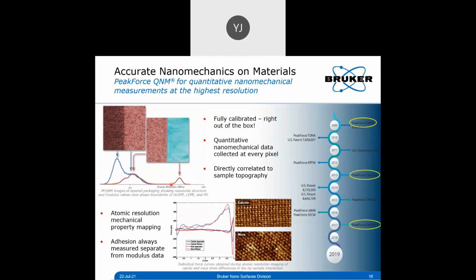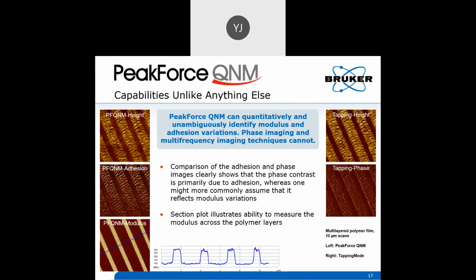Yeah. So now I want to talk about nanomechanics. With PeakForce Tapping you get a fully calibrated system out of the box. You get nanomechanical properties not just across the sample, but every pixel is nanomechanical data, right? Atomic resolution nanomechanical data that we saw before. When you do tapping mode, you get height and phase. You do not know what this means. But here you can see the height, the adhesion, the modulus, and other parameters, whatever you desire, dissipation, etc. This is all done in a single pass, right? So you do one scan, you get 8 different channels of mechanical data at the same time.